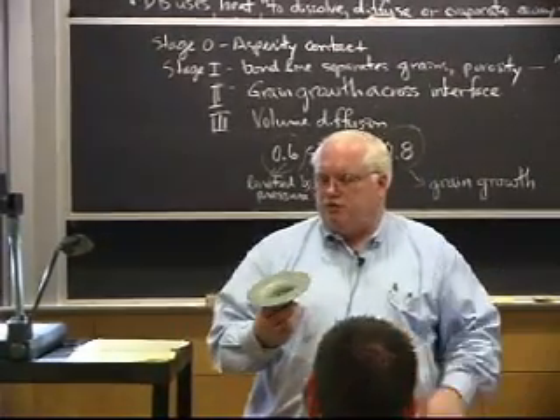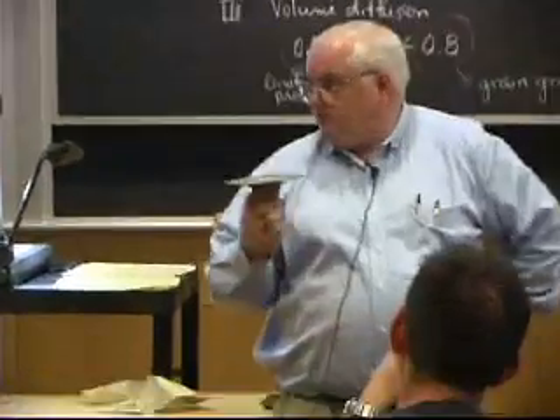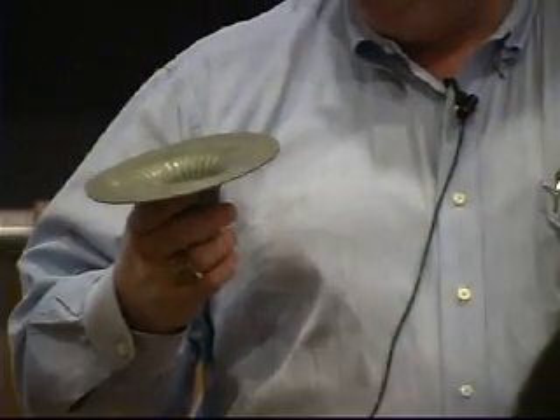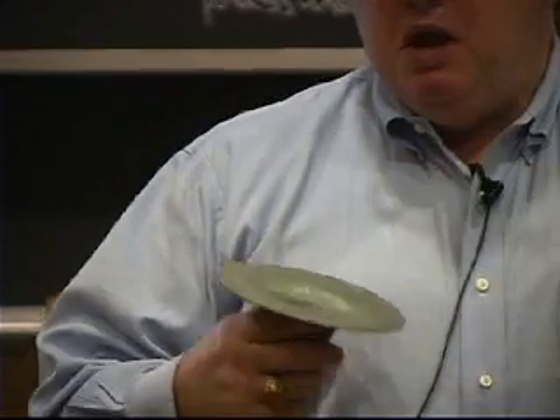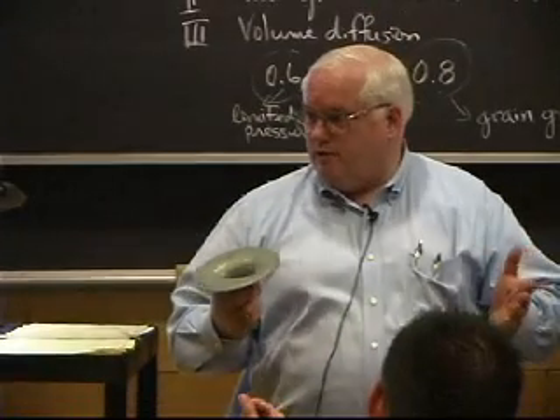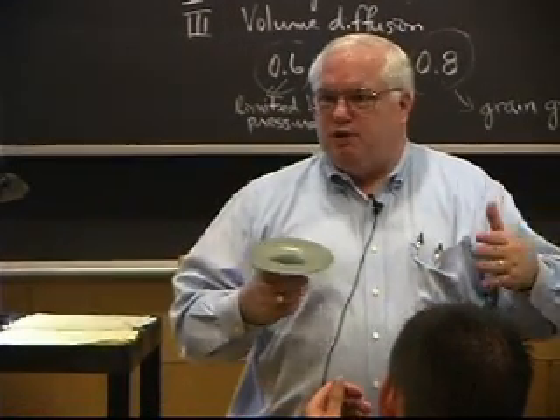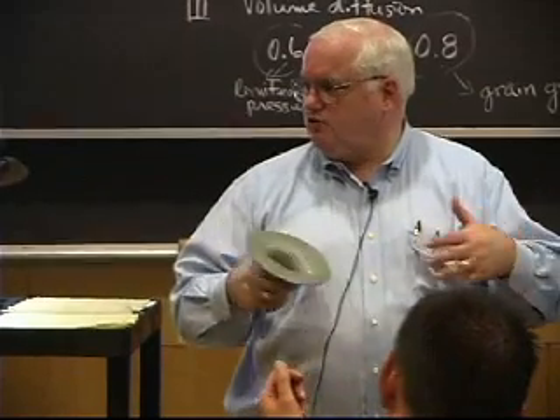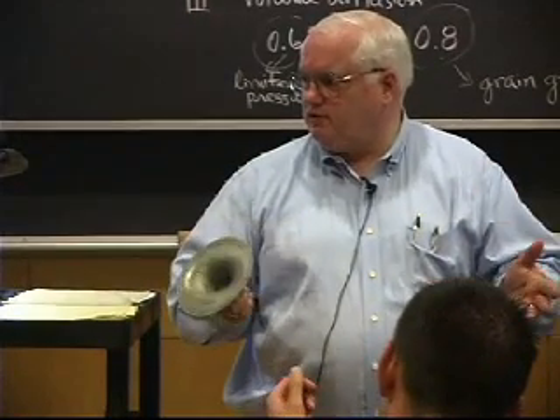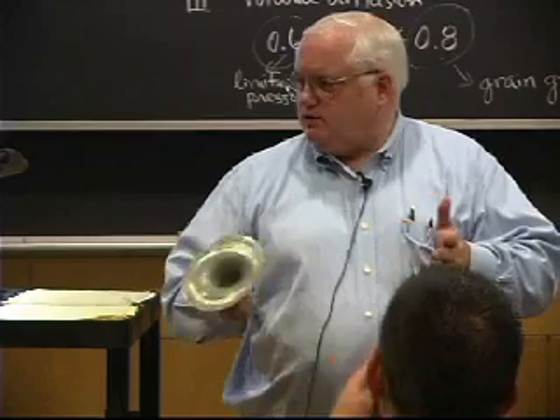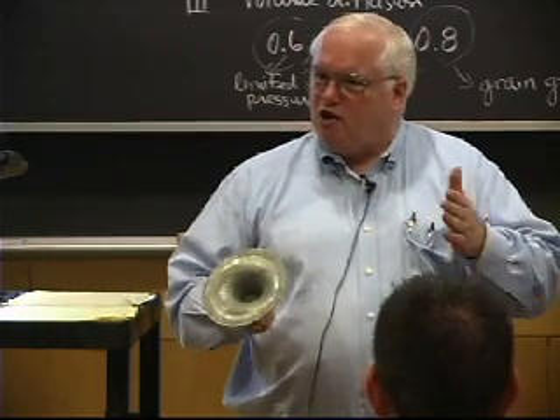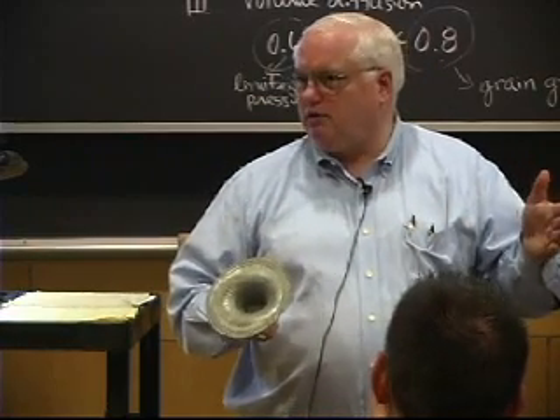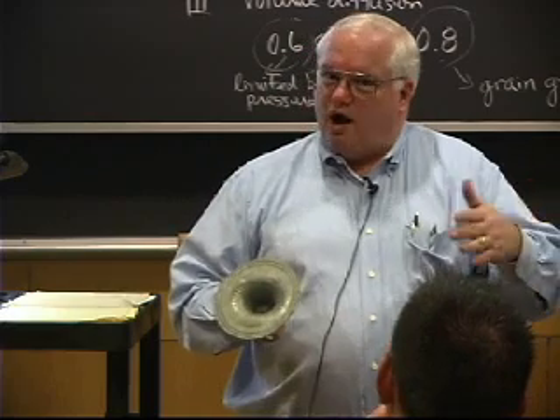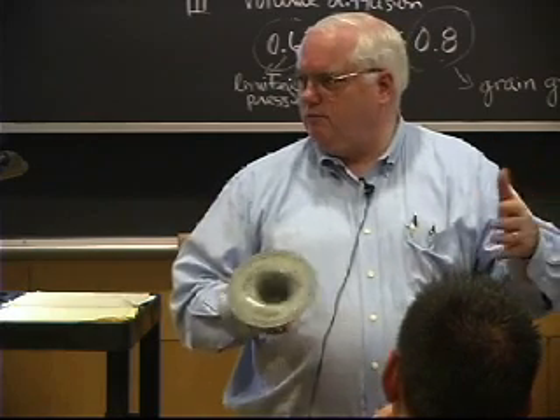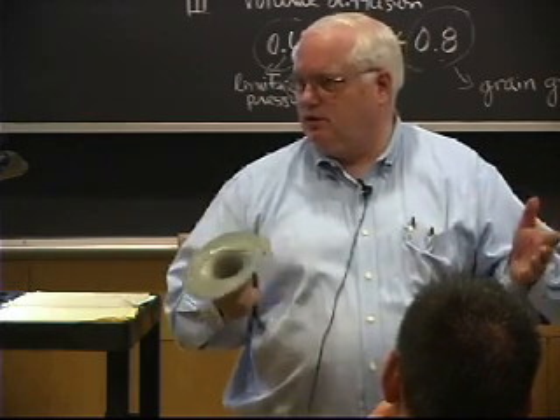I mentioned superplastic forming and diffusion bonding. We talked about titanium being very easy to diffusion bond because above 900 degrees C, it dissolves away its own oxide. And a little bit of oxygen in titanium is not harmful. In fact, you use oxygen in titanium to give it some extra strength, just like you use carbon in iron to give steel extra strength. Of course, it has the same type of effect. Carbon will make iron somewhat less ductile, a little more brittle, and oxygen in titanium will make the titanium a little less ductile and a little more brittle.